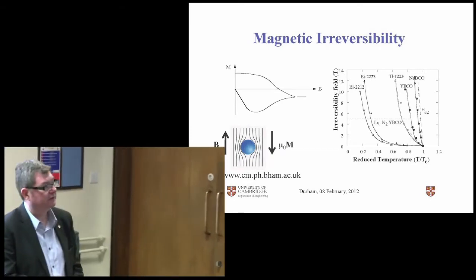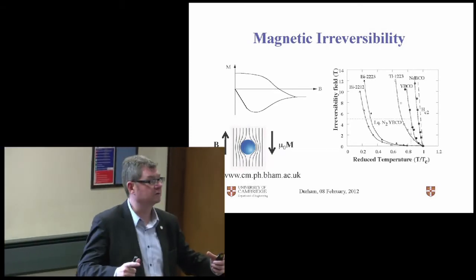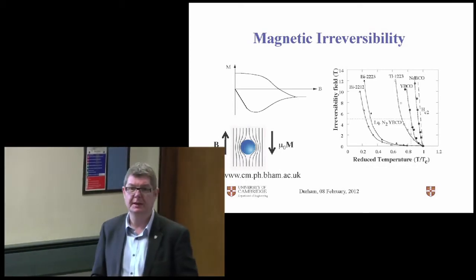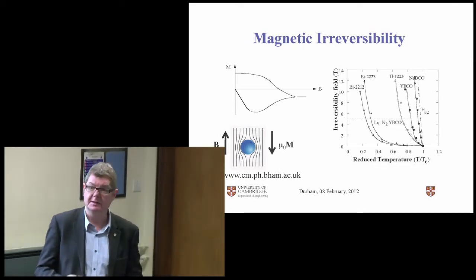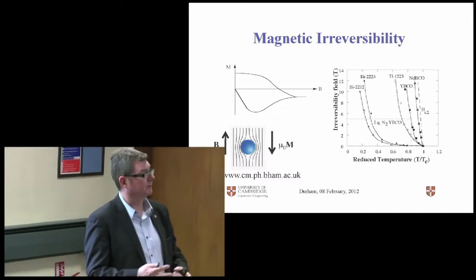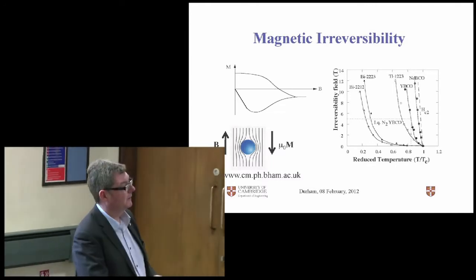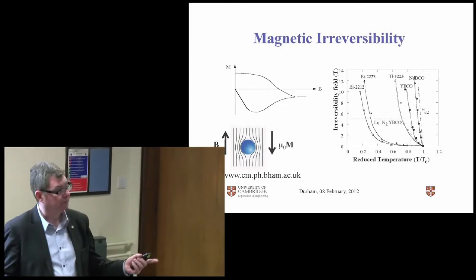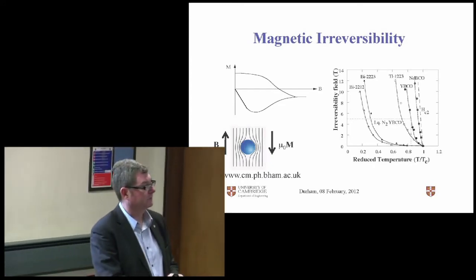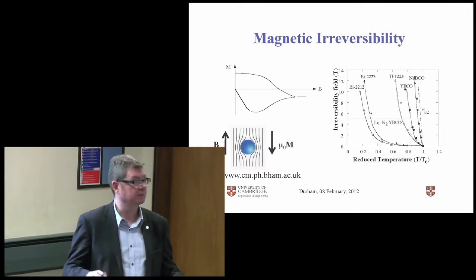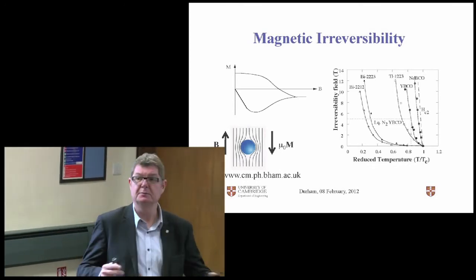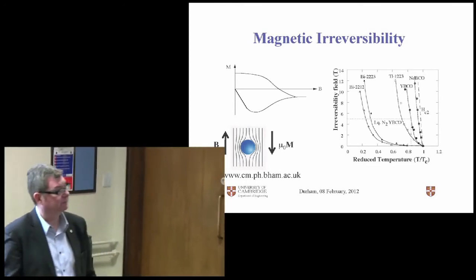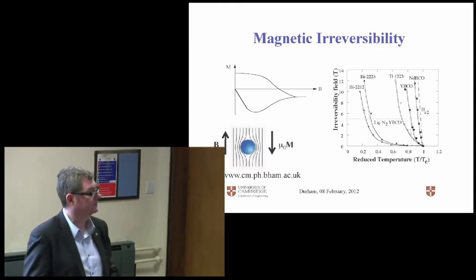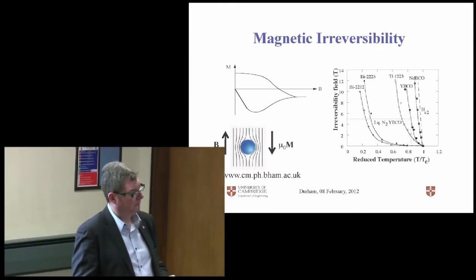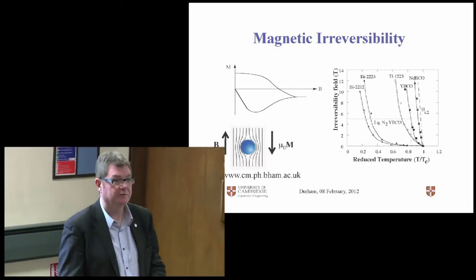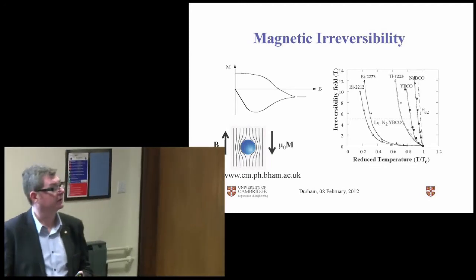And note that the magnetization therefore increases as you make your sample bigger. If you take a permanent magnet, where the magnetization is net magnetic moment per unit volume, you double the volume, you double the magnetic moment. So magnetization, all but for very small geometry samples, is independent of sample volume for a permanent magnet. So there's no gain in going to a bigger sample, whereas in a superconductor, the bigger you make it, the bigger the field it should generate. So the whole message is big samples carrying larger currents give you big magnetic fields, and that's where we're going.